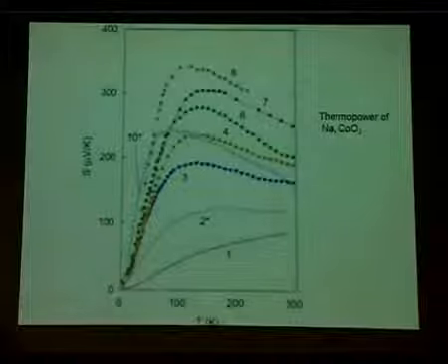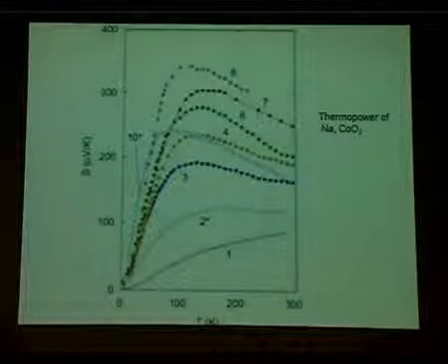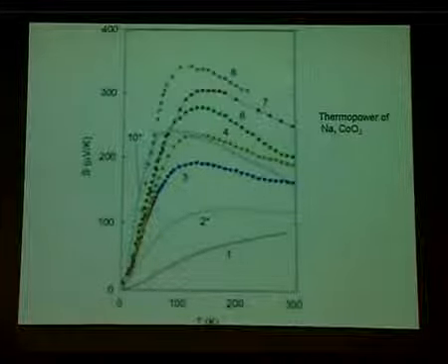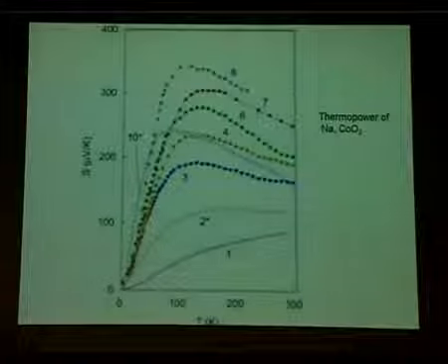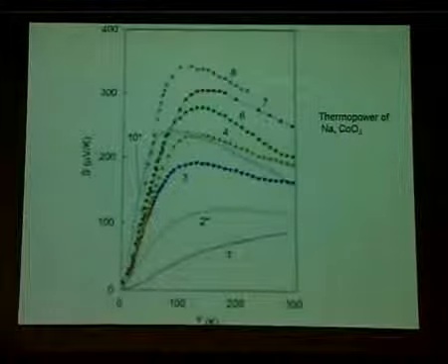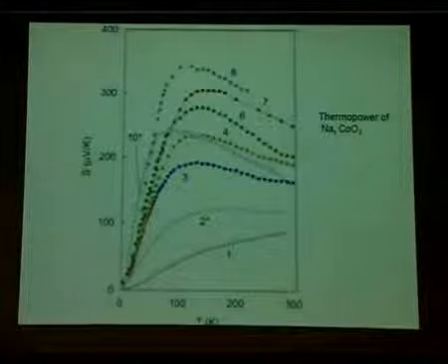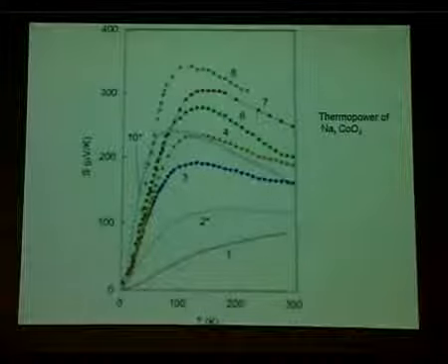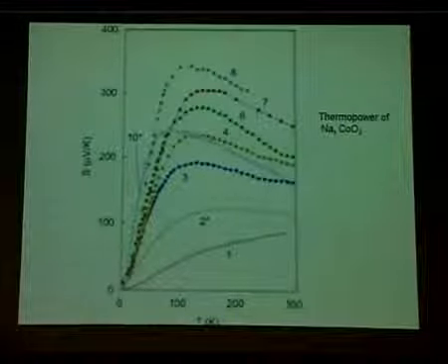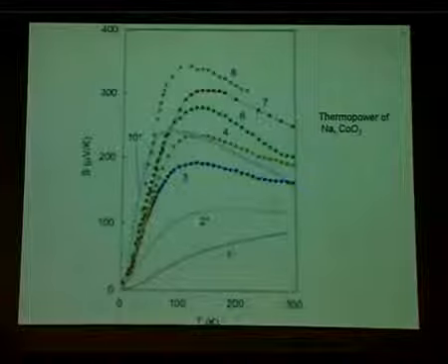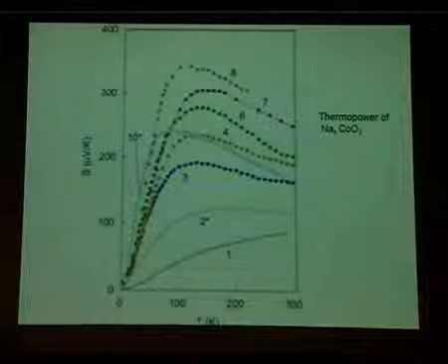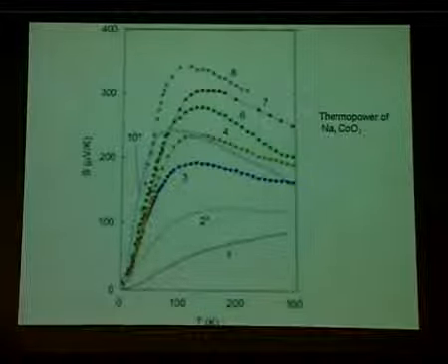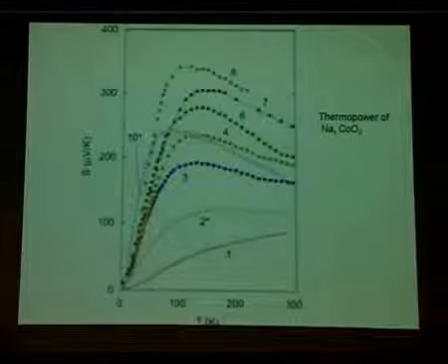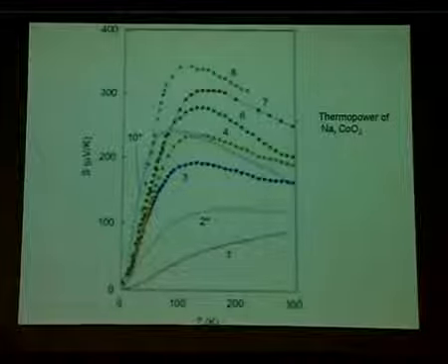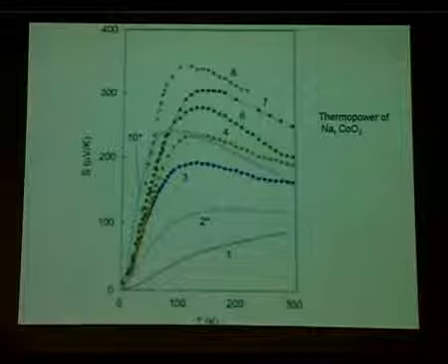We have been told that if you have a degenerate Fermi system, the thermopower, which is due to the entropy carried by the charged objects, which are electrons, will be proportional to temperature, because in a degenerate Fermi system there is hardly much entropy. It's highly ordered. Just some electrons at the Fermi energy are excited. So that is why it is proportional to temperature.